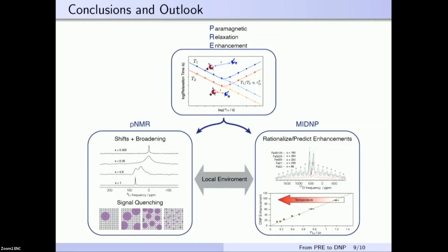But the difficulty here is that for DNP, we need long electron relaxation times in order to be able to saturate the forbidden transitions. But if this is the case, then the quenching sphere will be large, and we shouldn't be able to observe neighbors of the paramagnetic species. But that we are trying now, and hopefully some of them work.